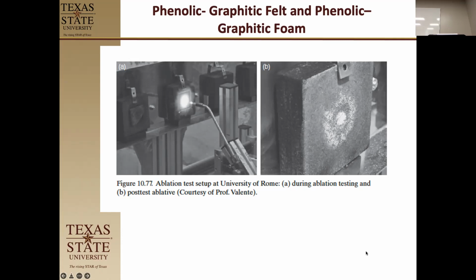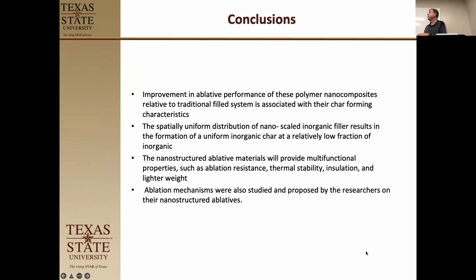Okay. That was for the film. This is for the foams, the felts, where they infused it with the film. And this particular one, I don't know which sample this was. It just gave that result. So what they found out was that the nano alumina helped their system slow down ablation.